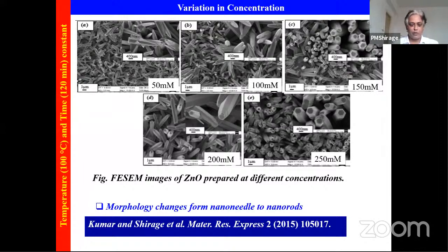Once we use this concentration and prepare the material, we scan it using the scanning electron microscope, which will provide the information about the surface morphology. We can see that at 50 millimolar, it's a needle-like structure. When we increase the concentration, that needle-like structure forms a tapered needle-like structure, then converts into a rod-like structure at higher concentration. It means that concentration is playing an important role and is changing the morphology of the zinc oxide, by keeping 2 parameters, temperature and time, constant.